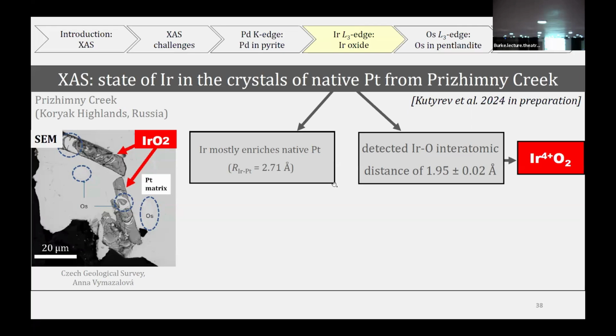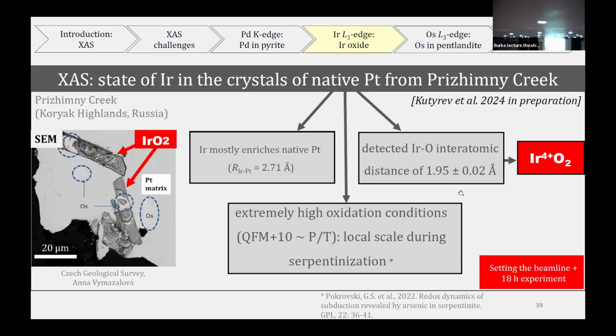But we also detected, by XANES and by EXAFS analysis, the contribution of iridium oxide with a typical interatomic distance of iridium oxide. Usually when we use both XANES and EXAFS, it's almost 100% success. So we are sure in this. And the interpretation is not finished yet because the paper is in preparation. So apparently it was formed in extremely high oxidation conditions, but probably that was the local state.